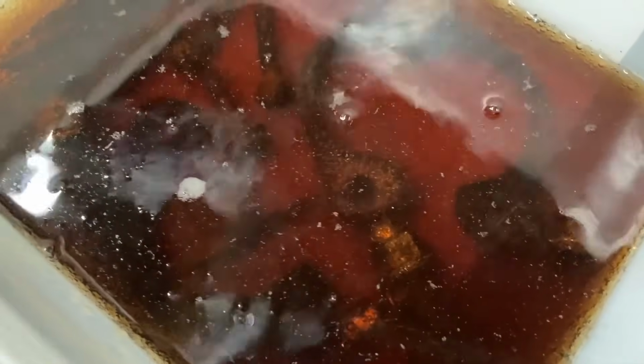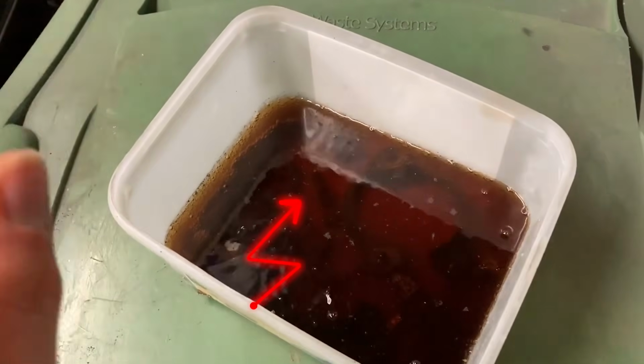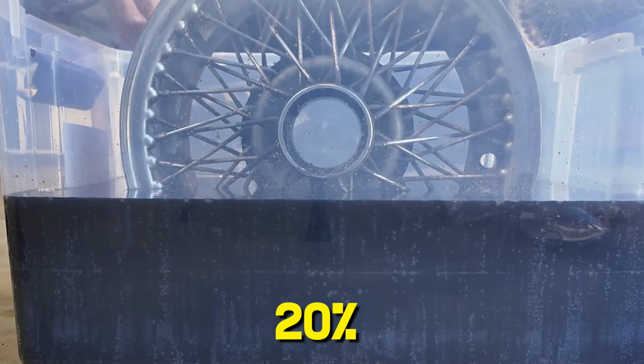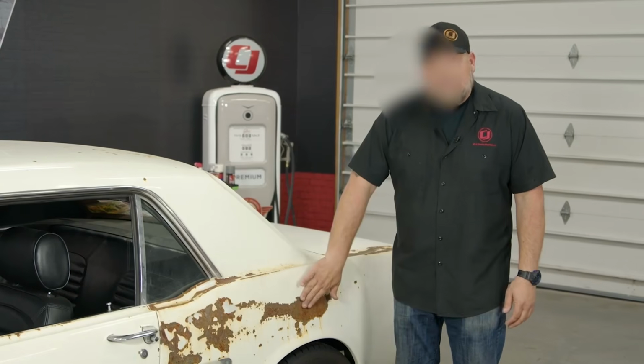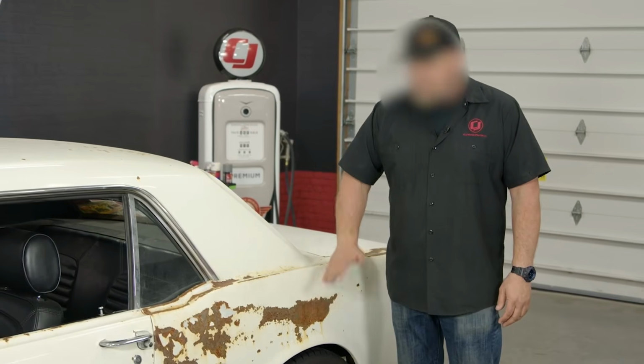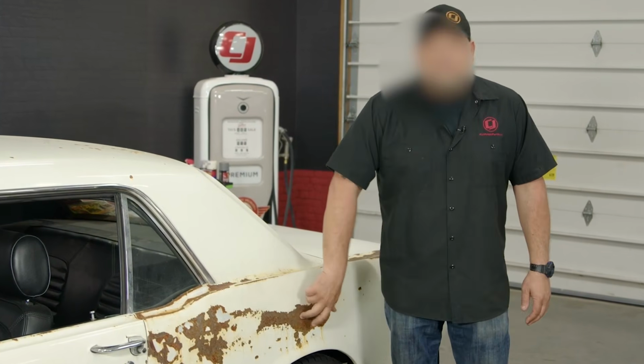On light surface rust with a thickened gel application held in contact for 45 minutes using plastic sheeting as a poultice, measurable rust removal was documented. On moderate rust with pitting beginning to develop in the metal surface, the gel poultice method produced approximately 20% rust removal at the surface level. The rust in the pits and below the surface layer remained completely untreated.